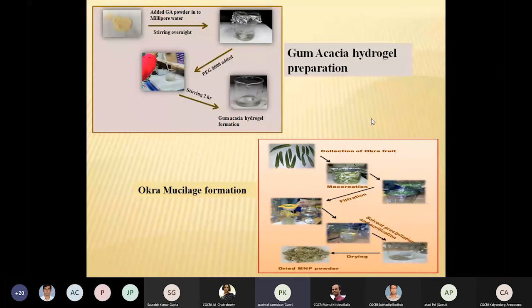And also we recently developed an okra mucilage, which comes from the common okra. So you cut the okra and incubate it overnight, and then you filter it so that the mucilage comes out, and then you prepare the hydrogel using solvent precipitation followed by drying, so you can get the dried mucilage powder, and this can be manipulated, which we are trying now to load with different kinds of drugs.